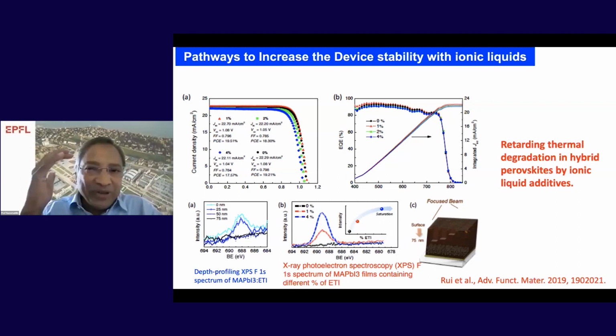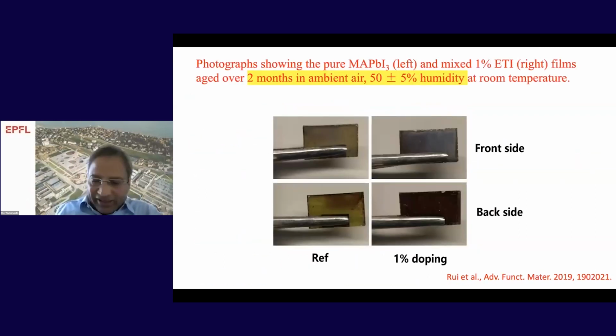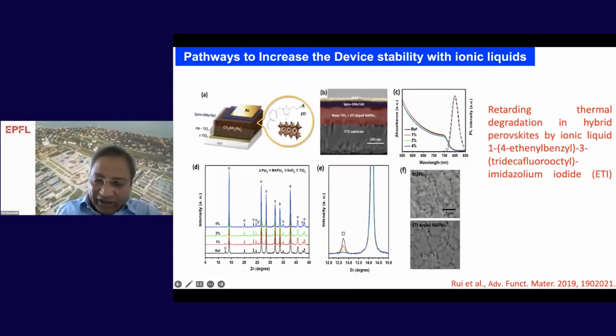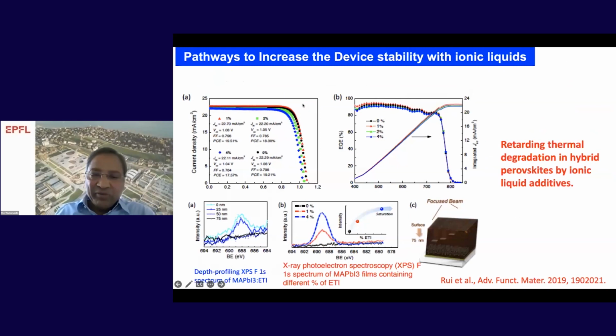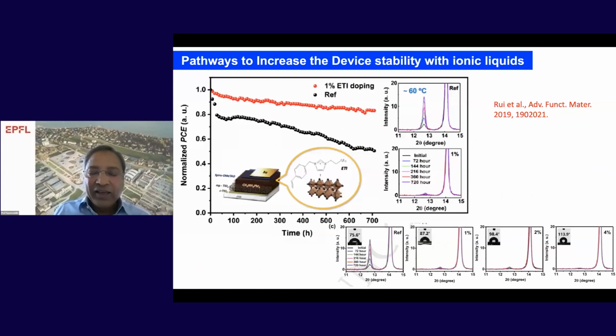Why should it form a shell on top of the perovskite grain? It's because of this octyl group, which has a fluorinated group, and these fluorinated groups float the molecule, and then when the crystallization forms, this ionic liquid is forming a shell on top of the grain. So this way you can increase the stability of the perovskite composition even at 60 degrees temperature.